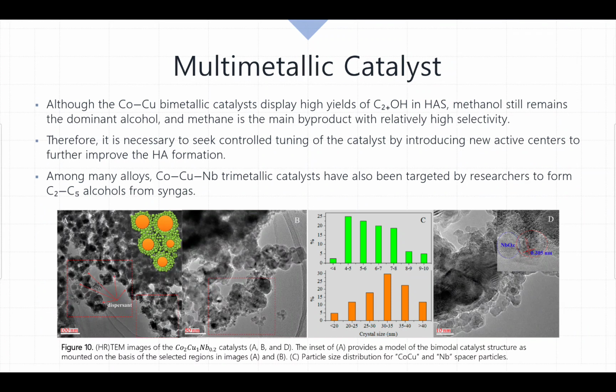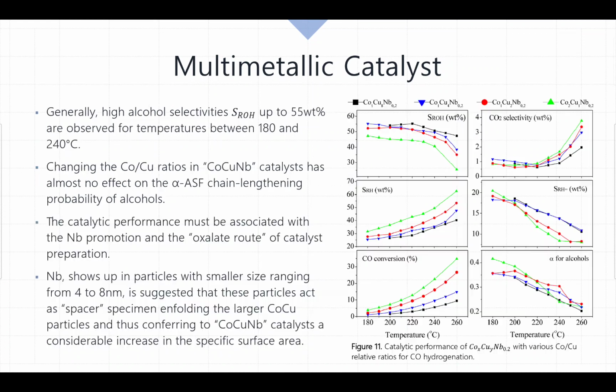Cobalt-copper-niobium trimetallic catalysts have also been targeted by researchers to form C2 to C5 alcohols from syngas. The bimodal nanosized particle distribution was achieved in cobalt-copper-niobium catalyst with smaller niobium oxides acting as a structural spacer to enfold the larger cobalt-copper particles, which results in an increased specific surface area. Besides, the strong metal-support interaction between niobium 4+ ions and metallic cobalt led to an enrichment of cobalt on the cobalt-copper particle surface, which could increase the concentration of surface CHx species for higher alcohol formation.